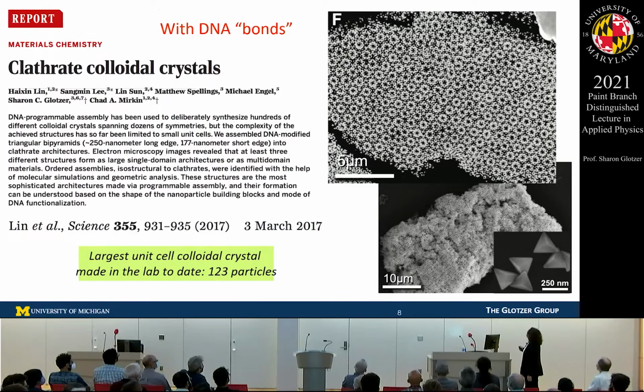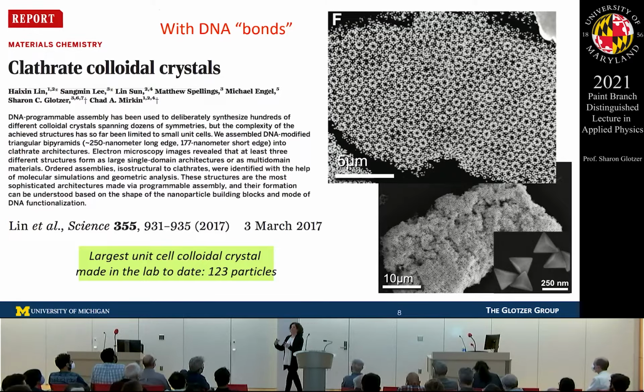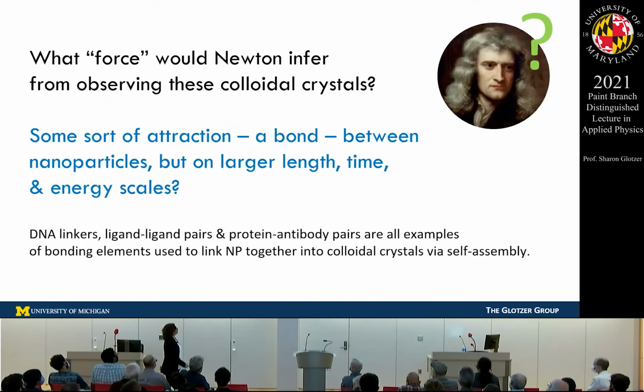And these particles are, again, functionalized with self-complementary DNA. The only real difference between this and the last one is that these nanoparticles aren't spheres. They have a shape to them. And because they have a shape, they self-assemble into something more complex than FCC. It turns out that they form this clathrate crystal structure with 123 particles in the unit cell. The reason why this was exciting is because it was really the first experimental demonstration that you could start to access crystal structures that are as complex as what we see on the atomic scale using nanoparticles.